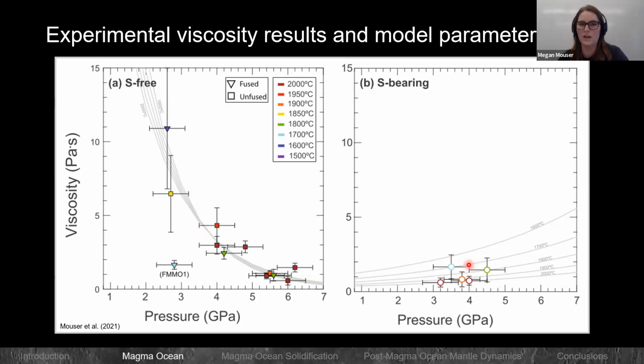in viscosity. And this was interesting because we thought that, well, if sulfur is in this really reducing system, it's expected to be an anion, a 2- anion. And it should primarily bond with network modifying cations such as calcium and magnesium. So if you're removing those from the system, you can allow that silicate portion to polymerize more. That was the hypothesis going in, and it appears that this is not quite the case here. So we wanted to at least look into this a little bit more.